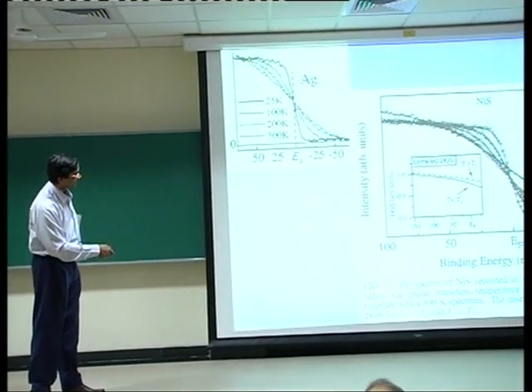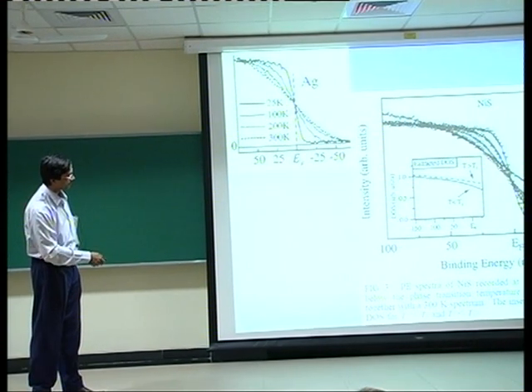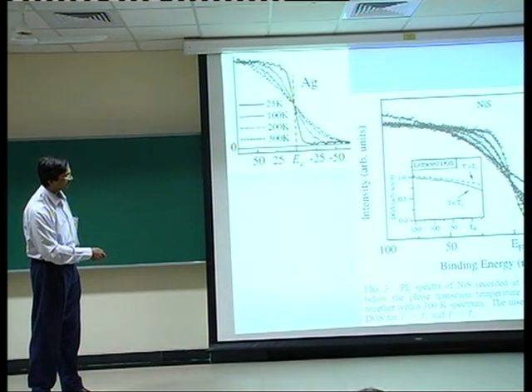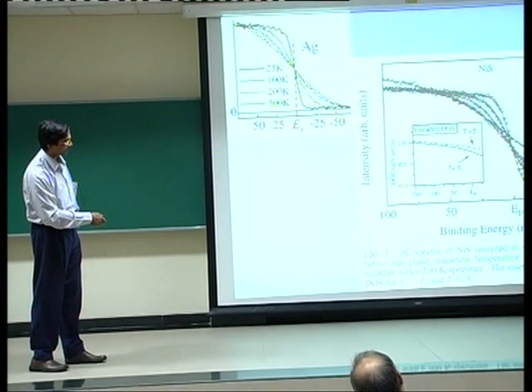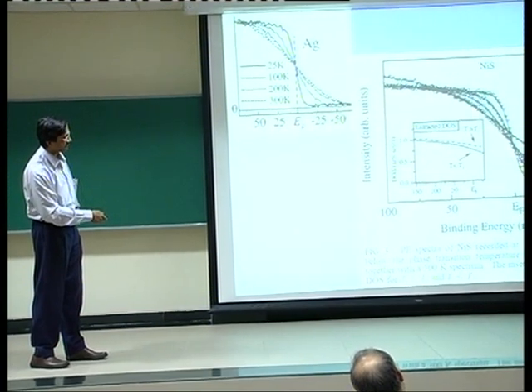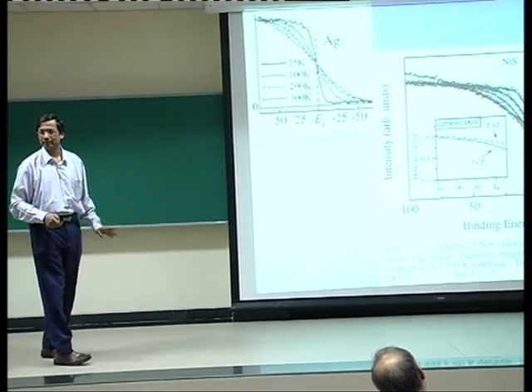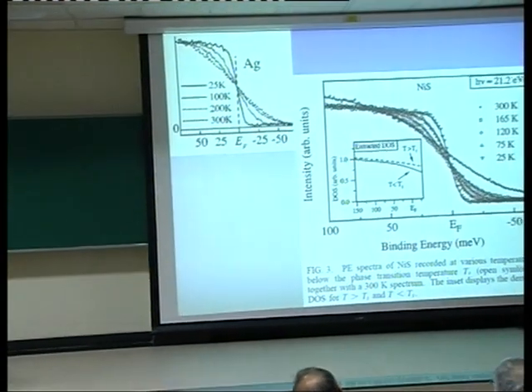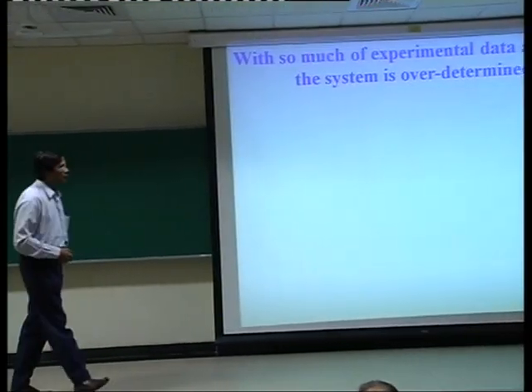What this line is that I told you to forget about is actually the room temperature spectrum, and immediately you can see that what happens between the room temperature and the low temperature is a spectral weight decrease at the Fermi energy and not a gap. And we have marked over here how much that drop is.